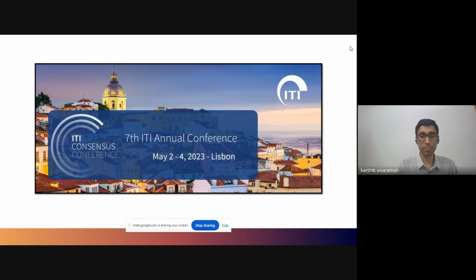And the first consensus statement mentioned that, from the available data, conclusions can only be drawn regarding the one-piece zirconia implant. According to the researchers and the clinicians who sat down for this consensus, they felt that the data available for two-piece zirconia implants is insufficient. The subsequent statements mentioned that the new commercially available zirconia implants have a better survival rate than the ones which are no longer in market and are at par with the titanium implants.